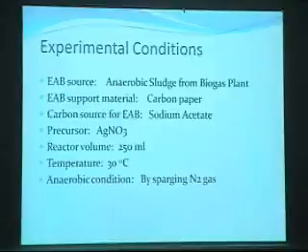And obviously we want to maintain the anaerobic condition, so we passed nitrogen gas for a short time, around 10 minutes, to make the anaerobic condition. So we just dipped our carbon paper into a solution containing anaerobic sludge, with sodium acetate as electron donor. After 2 days, we removed the anaerobic sludge and used only the media. That means in the second step, we didn't use the anaerobic sludge, just the carbon paper and our media. Then we kept it around 1 week, and made our electrochemically active biofilm.